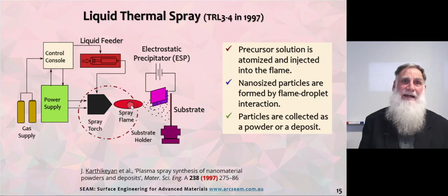And in about 1997, this was at the technical readiness level of about 3 to 4. And this shows you the setup that we're talking about. So we have a liquid feeder shown in red, essentially a perfusion pump that feeds a liquid and particles into a spray torch. These particles enter the spray flame, and they can either be collected by electrostatic precipitation or they can carry on unimpeded to impact against the substrate.